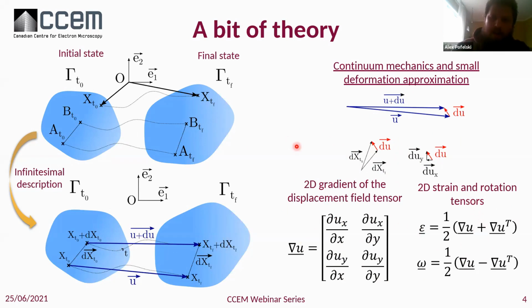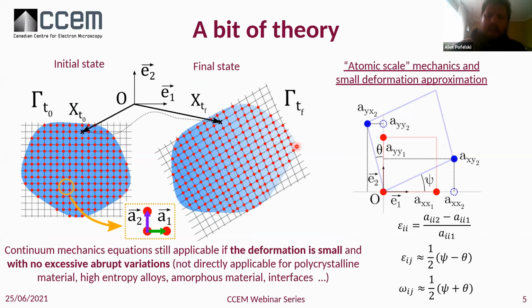So there are different ways of defining those elements. Here I just took the most basic ones, accepting the small deformation approximation. But the general idea is that when we go into the atomic scale, there are some comments that need to be made. First, we are technically losing the continuum because we are dealing with atomic columns. So we just have to be a little bit cautious when using those derivatives. The continuum mechanics equations are still applicable if we consider that deformation is small and there's no excessively abrupt variation. So in that context, this is not directly applicable, for example, for polycrystalline materials, high entropy alloys, amorphous materials, or interfaces. It's still okay to use it for single crystals.